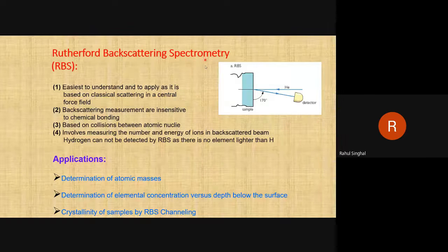Your helium ion will not come at a perpendicular angle of 90 degree. Now they will come at some glancing angle of 2 degree or 3 degree, so that they will hit the hydrogen, and then go in the forward direction. So this is a totally different technique. This is not backscattering, because now you are not measuring the backscattered helium ions. That technique is called ERDA, elastic recoil detection analysis. So if you want to measure hydrogen, you have to perform ERDA.